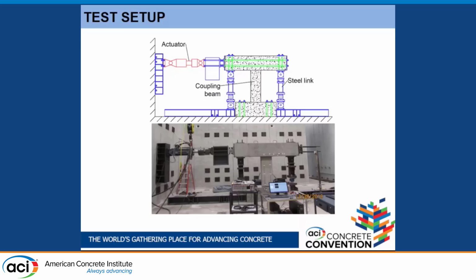We applied lateral displacements at the top horizontally, back and forth. Drift means the relative displacement of the top of the coupling beam versus the bottom. If I talk about drift ratio, that would be the relative displacement divided by the total coupling beam length. One important thing is that these links also provided some degree of axial restraint, which will occur in a real building, because you have the walls that provide some restraint against the coupling beam expansion, and also the floor slabs.